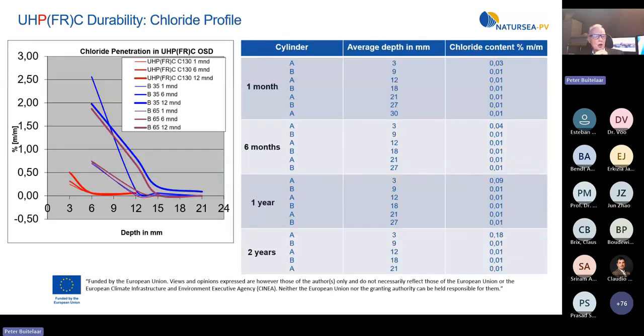Research for the strengthening of the orthotropic steel decks in 2002 confirmed that 2 years exposure to chlorides only resulted in chlorides in the top slice of the cylinder. We are talking about less than 3 millimeter. Unfortunately, the test had to stop due to the lack of enough samples.